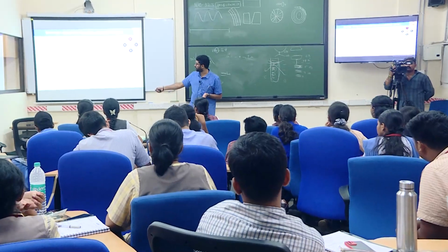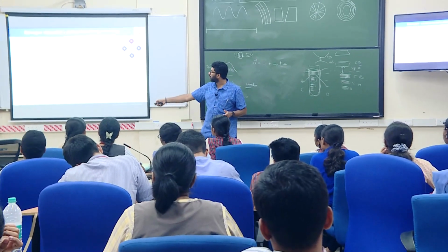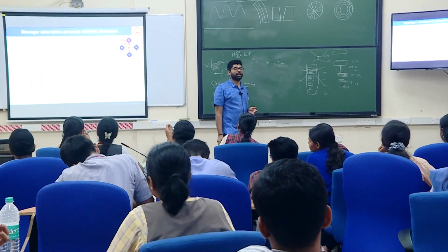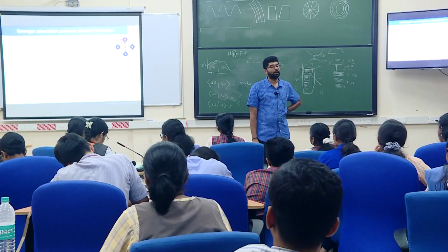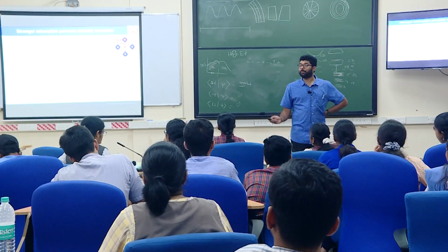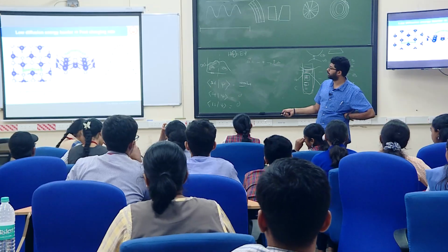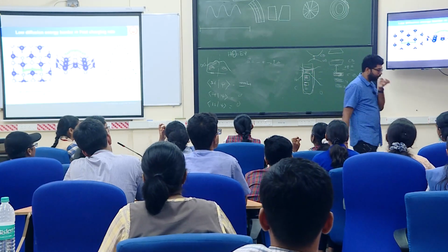So obviously potassium should have an easy migration. And between these two, minus 1.5 and 0.7, that is about 0.8 barrier. So the difference in energies between the sites is the important thing. That's what I tried to show here, but I think you got the major point.